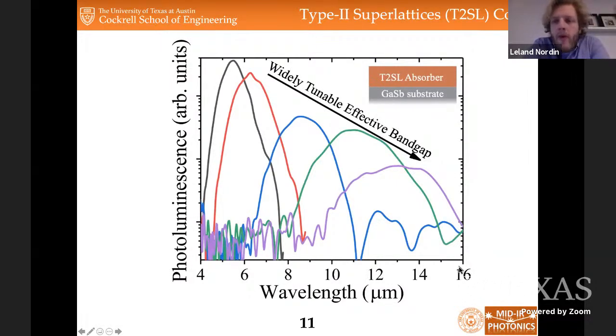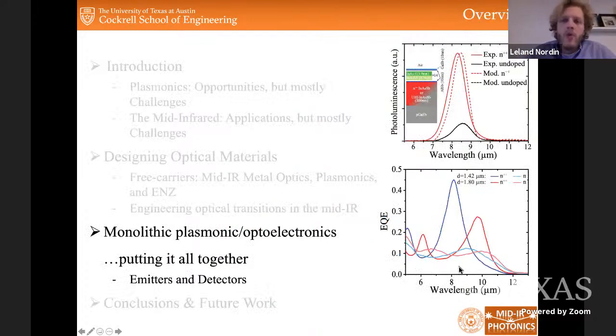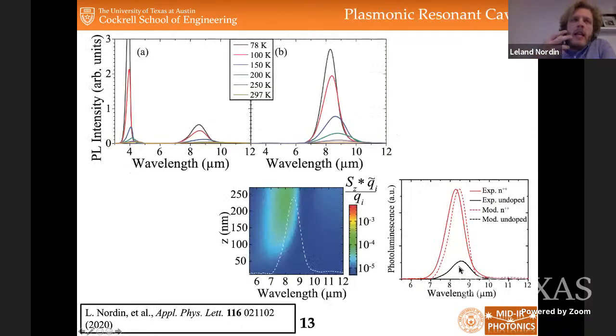So this is photoluminescence for a handful of type 2 superlattices that we've grown in the lab. And just like the doped semiconductors and their plasma wavelengths, we can tune all the way from 5 microns in the mid-wave infrared all the way out to 13 microns. So we have this really rich system to tune not only the optical response of our doped semiconductors, but also the electronic band structure of our superlattices. So what can we do as far as putting them together and making actually enhanced emitters or detectors and plasmonic optoelectronic devices? Well, the first question that comes to mind is that these semiconductors, optoelectronic devices specifically, often leverage high crystallinity.